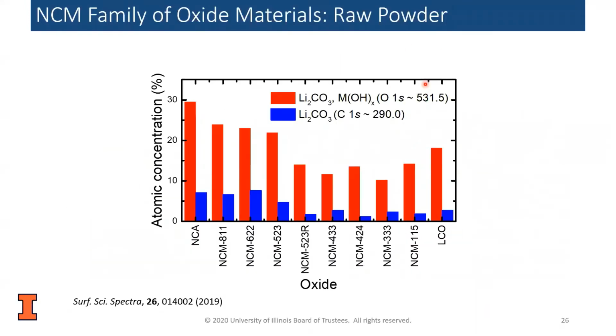So if you look at the ratio of the compositions, the high energy oxygen peak at 531 actually consists of lithium carbonate, and also metal oxides, mostly lithium hydroxides. Having a lot of lithium hydroxide available at the surface makes the electrode prone to decomposition, because that's very reactive to the carbonates that are in the solvent.